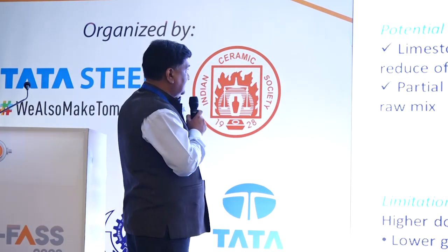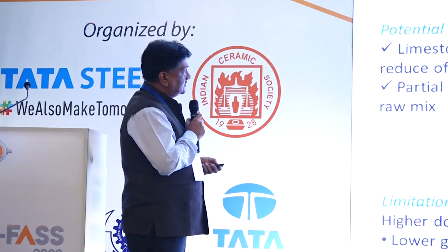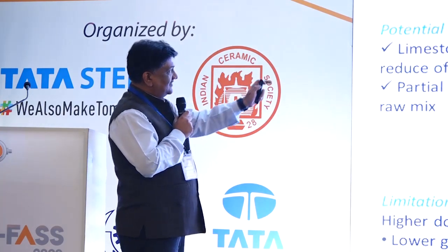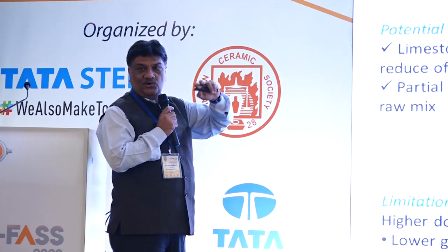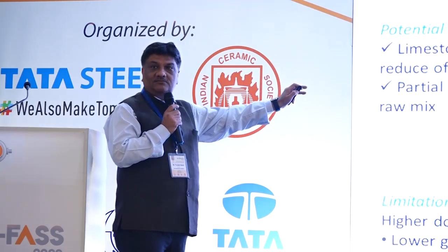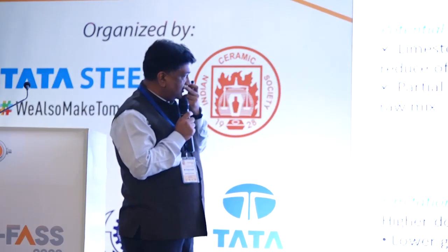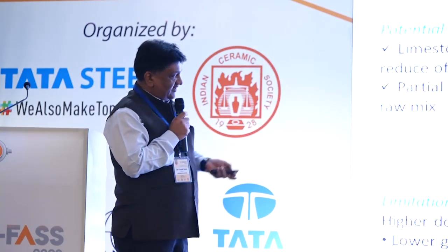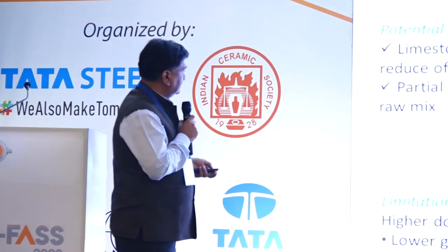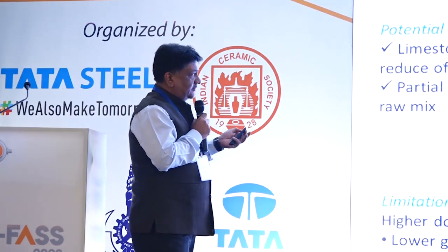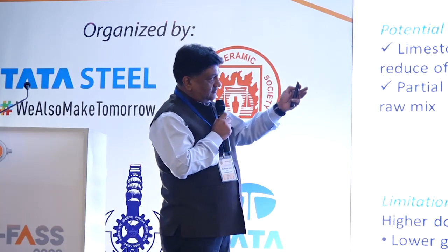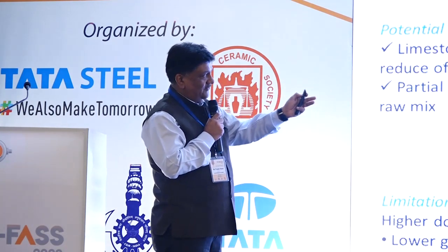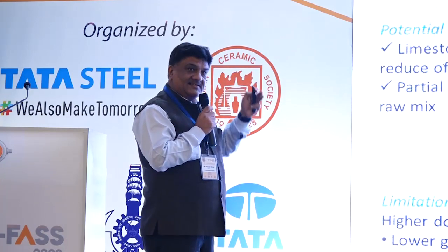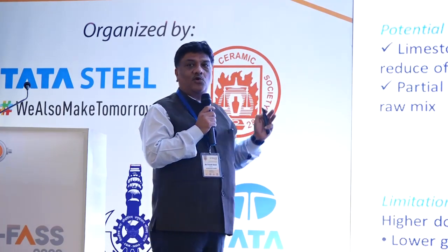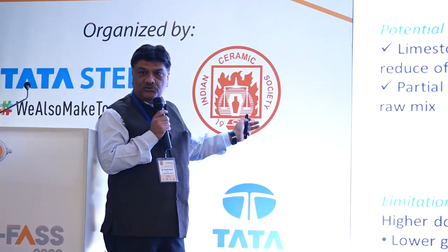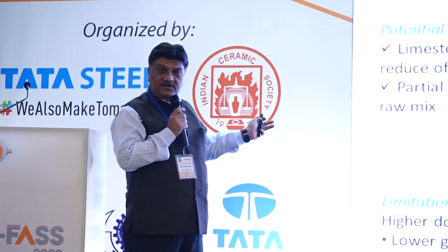There are some analyses. First, as I said, the raw mix component, you can see the challenge is the glass content. We were talking about what glass content we observe. That was 10 to 15%. And of course, the Bond work index, 25 to 28%. So that's the main problem. However, the ferrous is 15 to 25%. But adding this as a raw mix component, there won't be much challenge. You can always do it. It's about what mix you are designing.